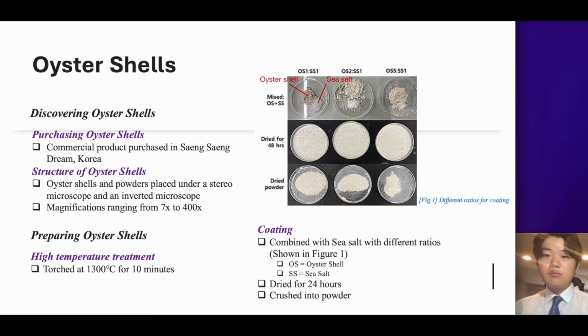There are 2 types of preparation of oyster shells as a de-icer. One method is based on heat treatment, in which the oyster shells were heated at 1,300 degrees Celsius for 10 minutes and ground. The other method is the salt coating method, in which sea salt and oyster shells are mixed at various ratios. With this method, different names are given depending on the proportion of sea salt and oyster shells for coating. OS stands for oyster shells, SS stands for sea salt, and the number in the middle indicates proportion. For example, OS1 SS1 refers to a mixture of oyster shells and salt in a 1:1 ratio, and OS2 SS1 is a mixture of oyster shells and salt in a ratio of 2:1.